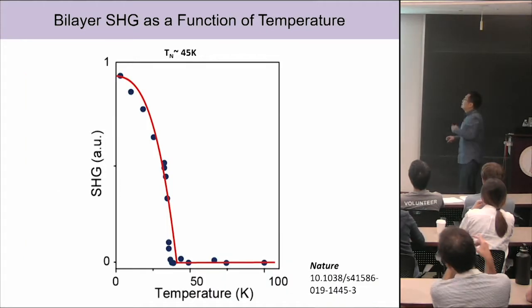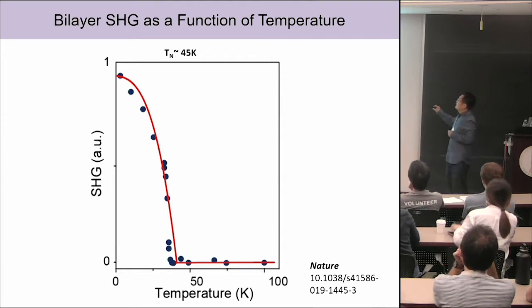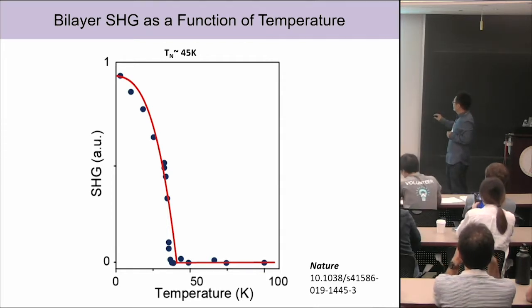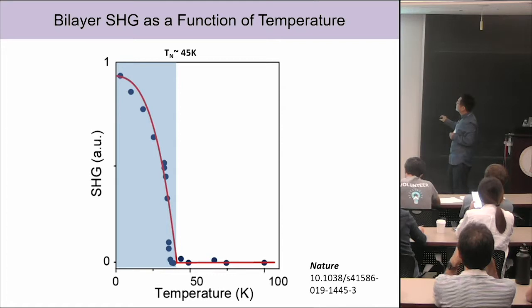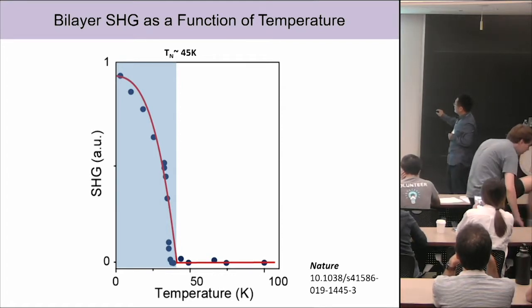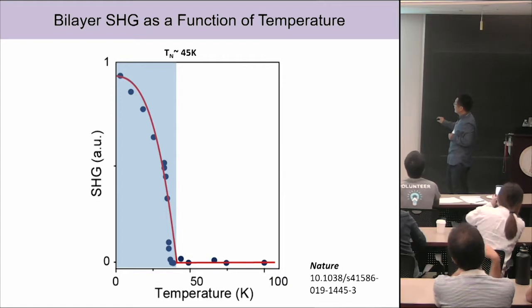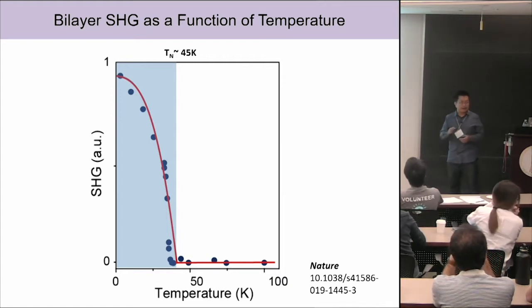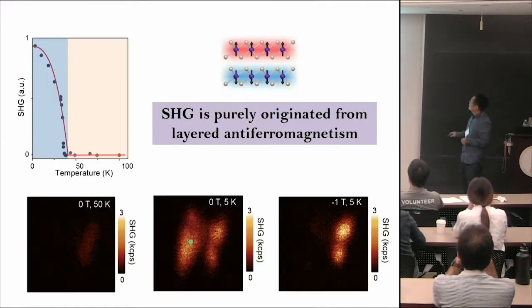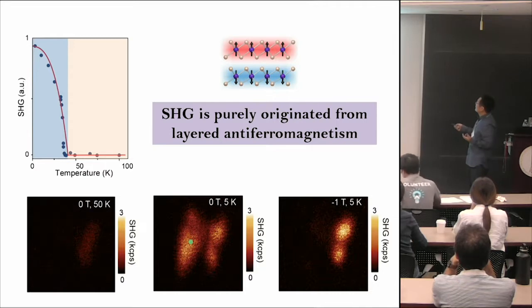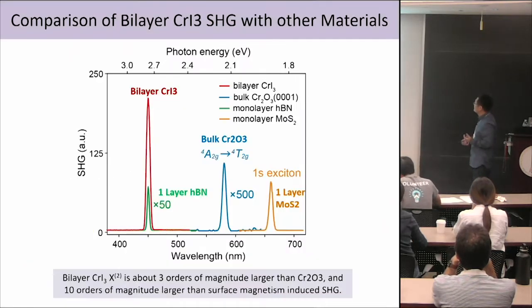And we can also map the signal strength as a function of temperature. So below the critical Neel temperature, the signal is strong, but it drops as we warm up, until it vanishes as the magnetic order also vanishes. Okay. So this demonstrates the second harmonic generation we measured is really coming from this layered anti-ferromagnetism.